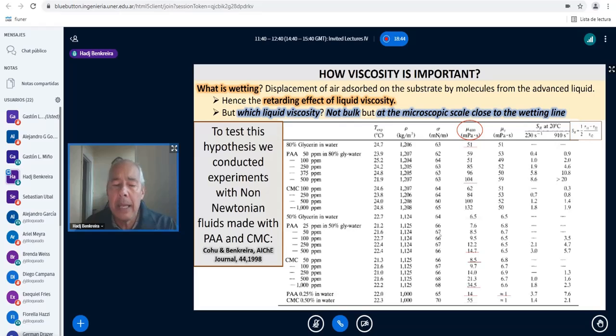And that is our first observation that we did. And we thought, okay, if this is the case, then if we are going to do air entrainment measurement with a non-Newtonian fluid, we should be surprised to find that the bulk viscosity of a non-Newtonian fluid does not really affect the air entrainment speed, but it is the viscosity of the solvent fluid that is going to affect the air entrainment. And I will explain this very clearly.